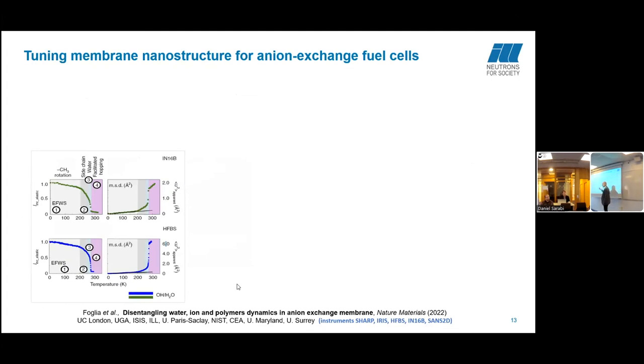So I'm not going to go into detail here, but they collected elastic data first, and we saw the intensity of the data changing. With backscattering experiments, you usually freeze your sample and then you bring it up in temperature. And as you increase the temperature, different motions start at different times. So they increased the temperature, and then we saw the elastic scattering decreasing because of rotations of methyl groups on the polymer backbone. And then at a different regime, they saw a significant drop in intensity due to the side chains of the polymer starting to move about. And then another change as water started to move about. And then finally, we actually saw hydroxyl ion popping at high temperatures for the first time.